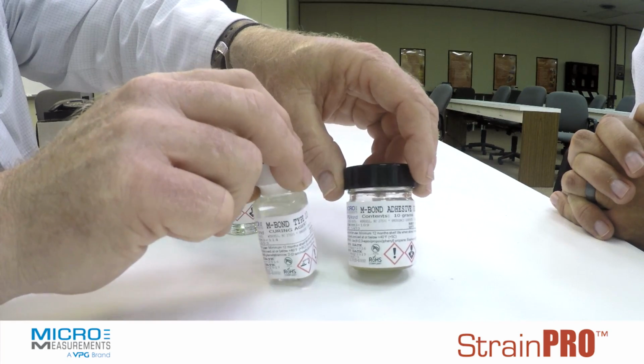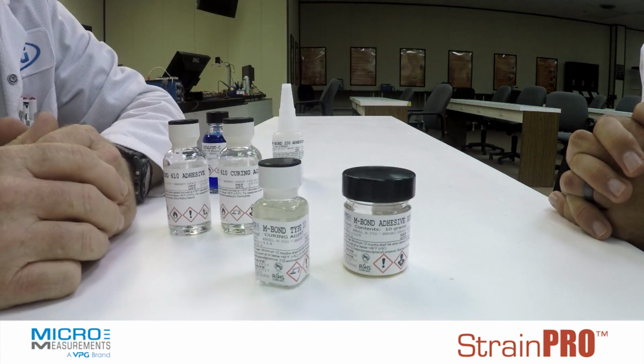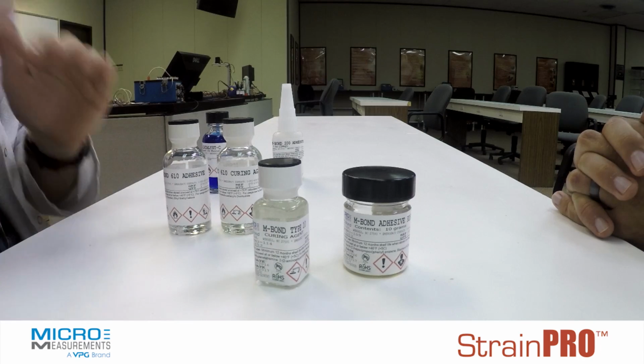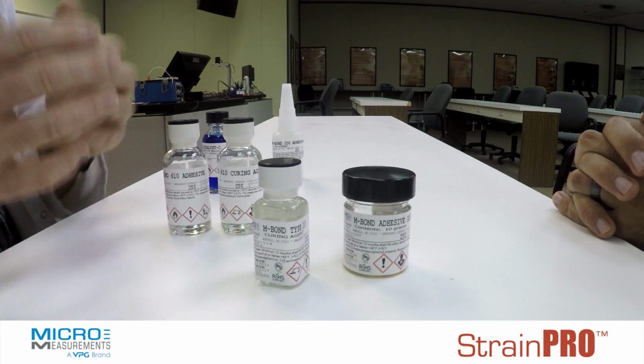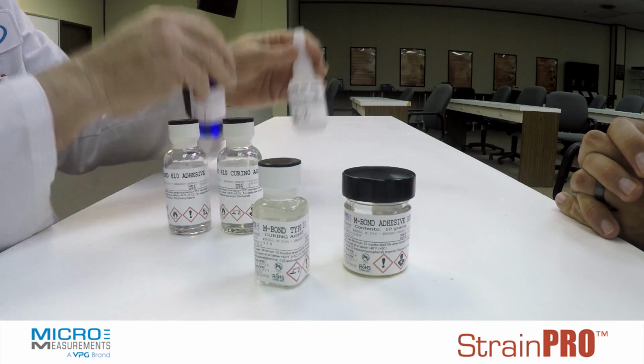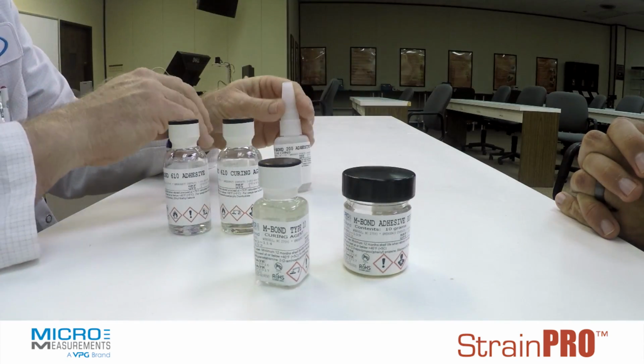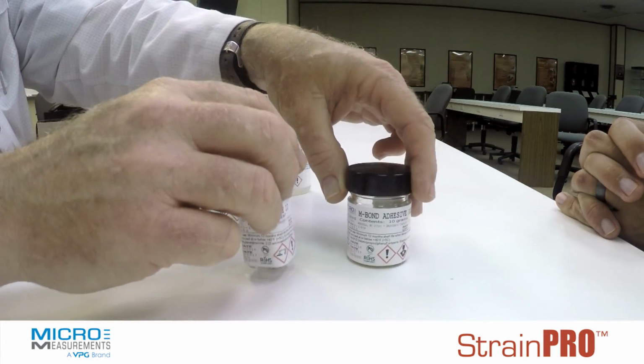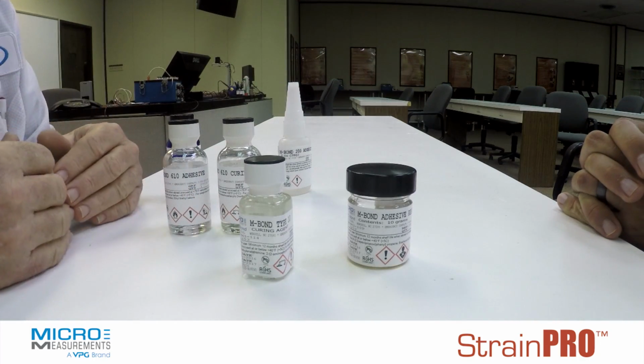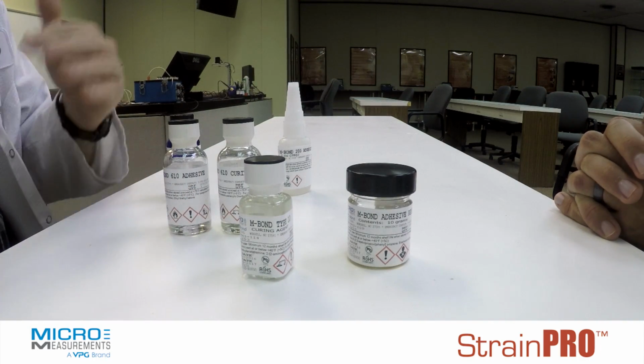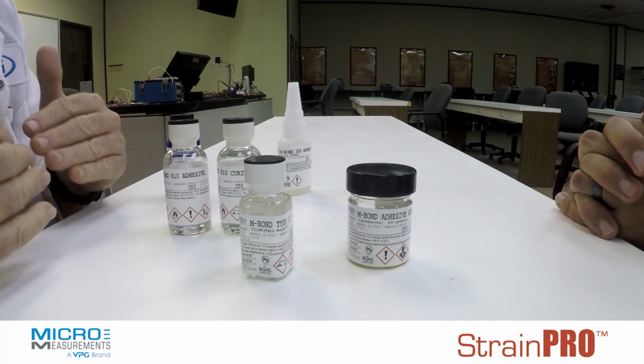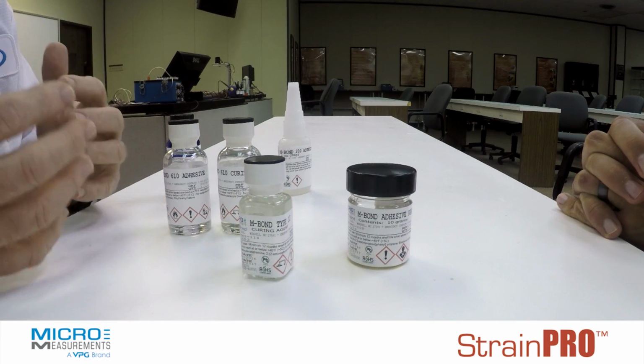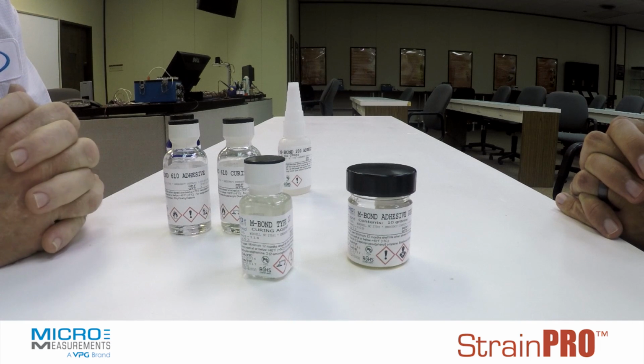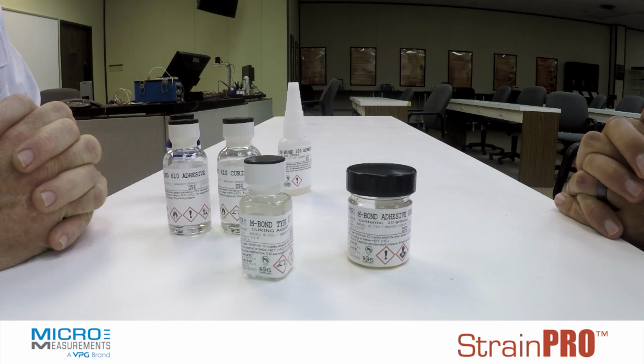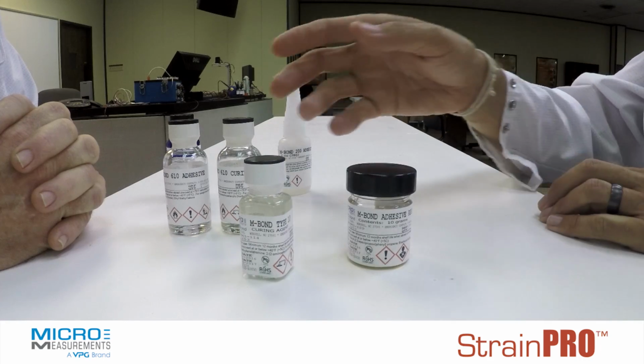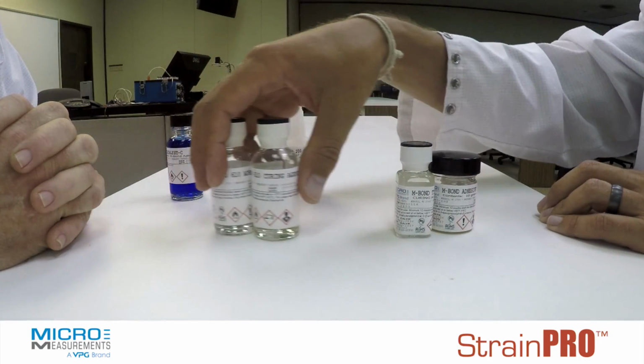They're excellent fillers to fill the voids within the surface of the material, and then you just lightly sand to present the parent material again, and then bond with the appropriate adhesive system, which could maybe be the M-Bond 200, or using the AE10 or AE15 again as the bonding adhesive. This way you fill the roughness of the surface, because the strain gauge can't conform to that roughness and it won't starve the bond line, and yet you can still have a room temperature curing adhesive system if you use AE10 or AE15.